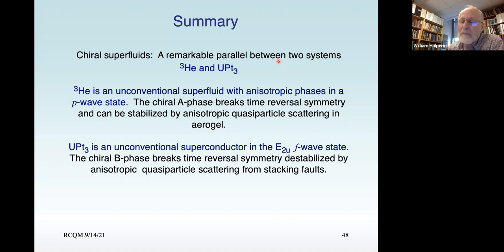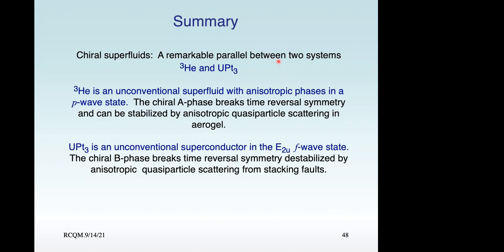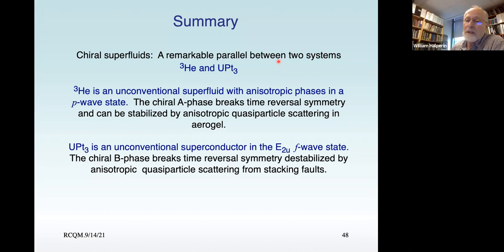I mean, the heat capacity measurements definitely tell you that there is a heat capacity residual that depends on temperature in the low temperature limit. You wouldn't expect that unless there are bound states, Andreev bound states at the surface, and the Andreev bound states at the surface are effectively Majorana states.